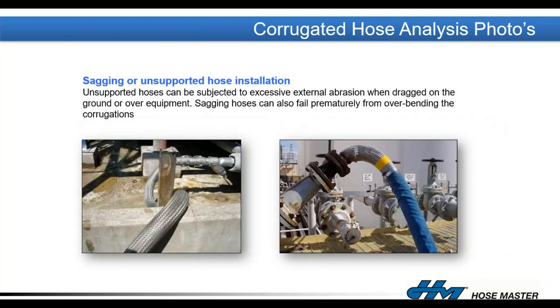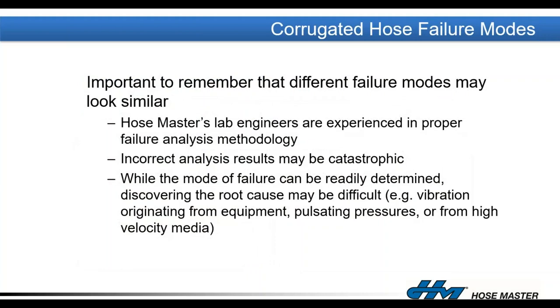Avoid any situations where the hose is going to be dragging against the parapet wall or that piece of angle iron on the left-hand photo, or if it can't be avoided, then you need to put some external protection on that hose. The hose on the right-hand side was installed so that it's going to naturally be overbent in that application. Why they would install a hose with that connection facing up in the air instead of 45 degrees down towards the ground is beyond me, but that hose is destined for premature failure. We can add a strip wound armor guard on the outside of that assembly to help protect it from overbending in that application. But see how the braid has bulged away from the hose? Again, that's an indicator that hose has been overbent.